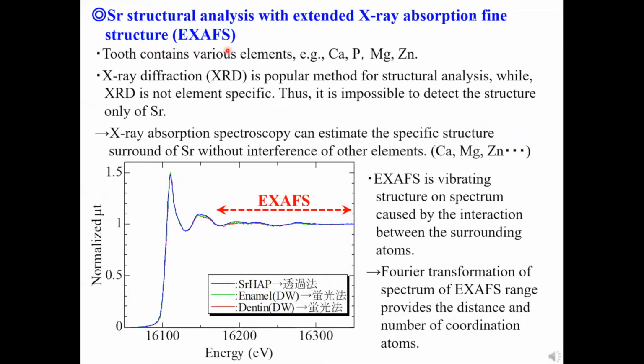The oscillation structure of the extended range after the absorption edge is derived from the resonance of the photoelectron among the target atom and surrounding atoms. Then, the analysis of this structure provides the distance and number of coordination atoms. With this method, we can estimate the absorbed strontium structure without interference from other majorly contained atoms such as calcium and phosphorus. The X-ray absorption around the edge is element-specific. Then, this absorption was caused only by strontium. And the oscillation structure around this energy range reflected the surrounding structure of strontium.